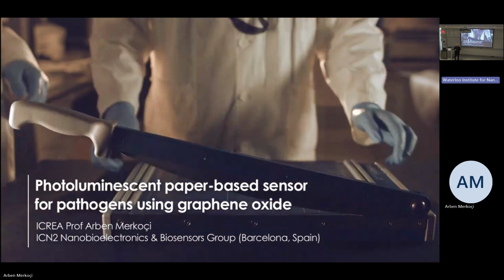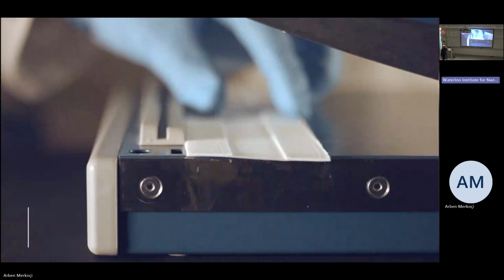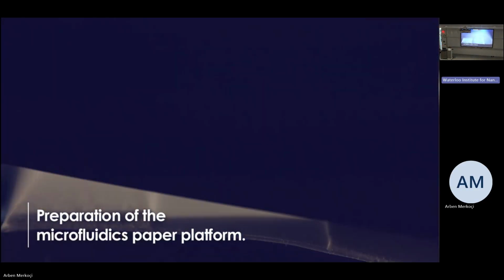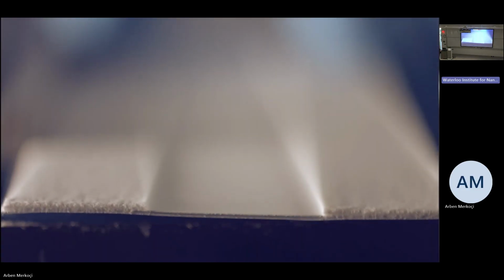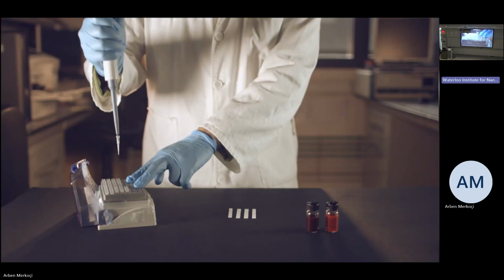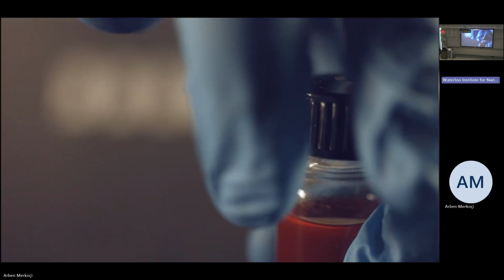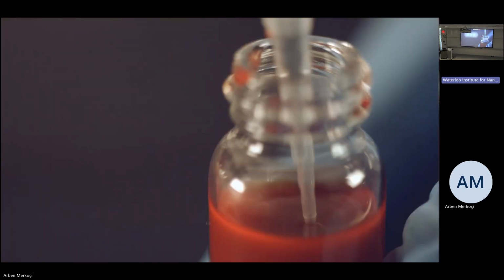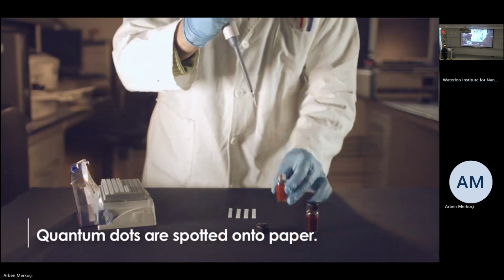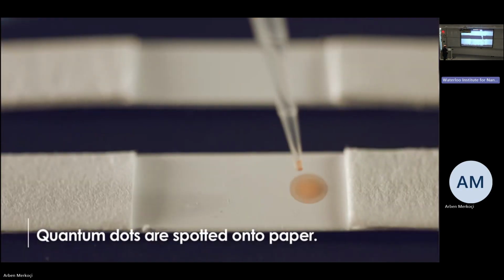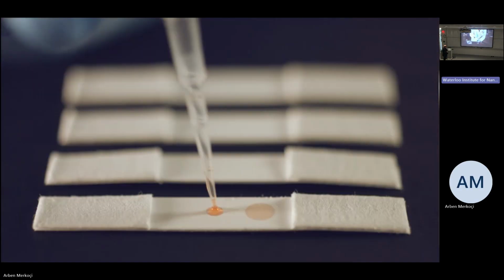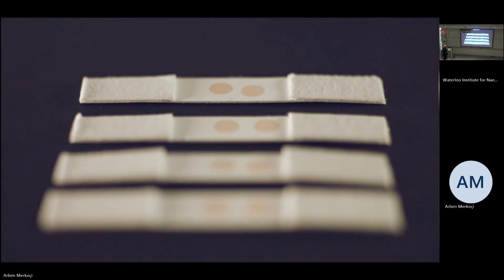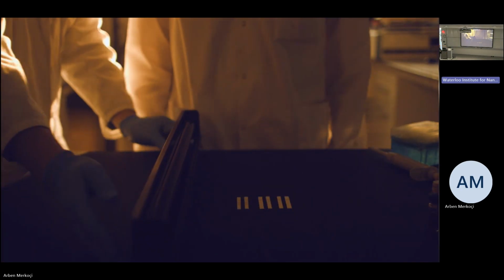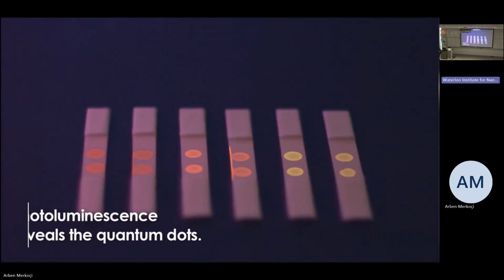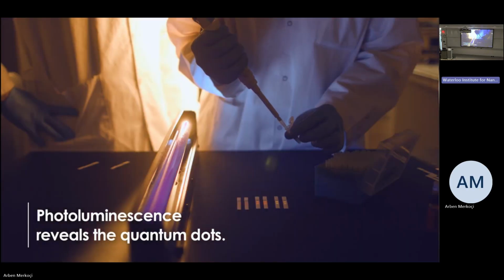So we prepare the paper. We are cutting here with a guillotine. Now we are using a laser to cut it better. This happened more than 10 years ago. But just to see the operation principle, we introduce cadmium selenide quantum dots onto the paper. You will see after exciting with UV visible, the nice photoluminescence coming from cadmium selenide quantum dots. So excitation now, and you see the nice color coming from the cadmium selenide quantum dots.